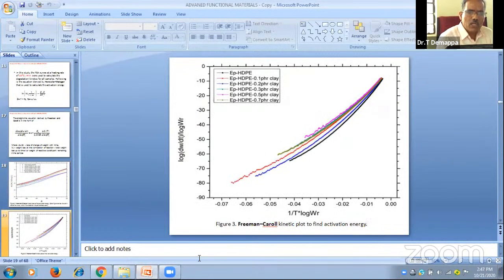See another Freeman and Carroll kinetics model or method. This is also the logarithm of dW by dt against the logarithm of WR divided by 1 over t into the logarithm of WR. We approximately get a straight line to take a slope. Even if we don't get a straight line, we can take a tangent to that, then we calculate the slope. The slope gives you the energy of activation EA, and the intercept, extrapolated to that, gives you the order of the reaction.